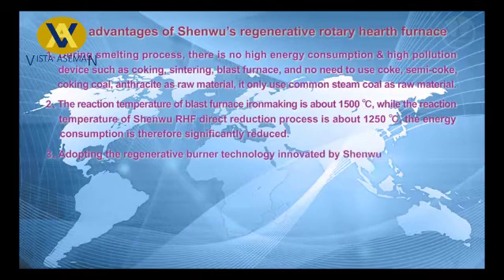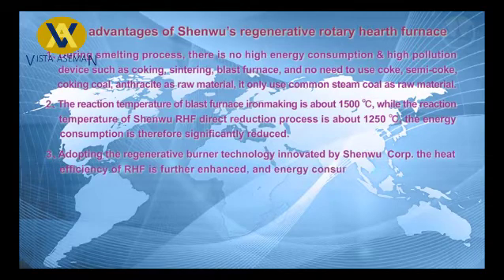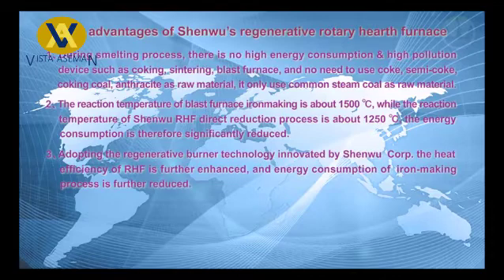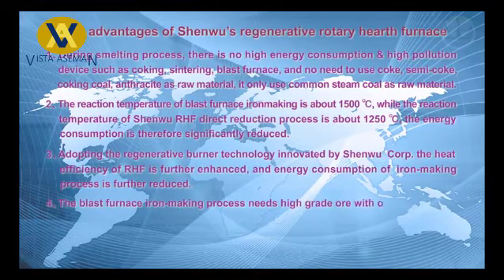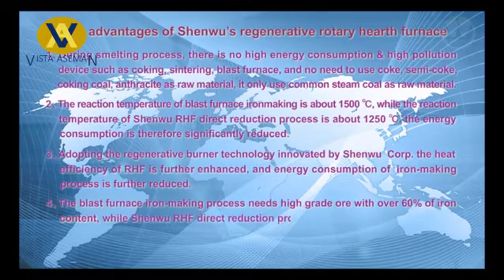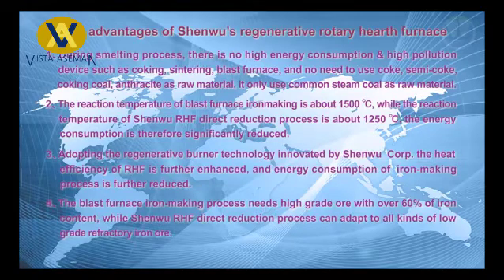3. Adopting the regenerative burner technology innovated by Shenwu Corp, the heat efficiency of RHF is further enhanced, and energy consumption of the iron making process is further reduced. 4. The blast furnace iron making process needs high-grade ore with over 60% of iron content, while Shenwu RHF direct reduction process can adapt to all kinds of low-grade refractory iron ore, composite associated iron ore, lateritic nickel ore, and iron-bearing solid waste of the non-ferrous metallurgical industry.